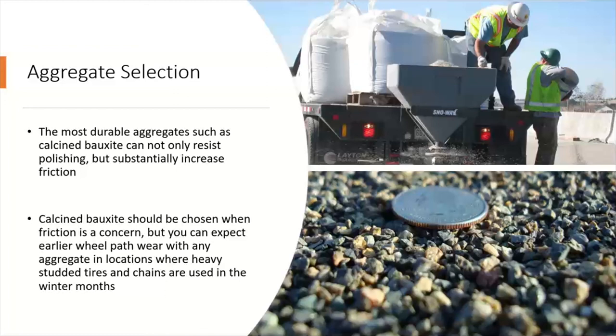It's calcinated and heated up to 1800 centigrade, and it's 87% aluminum oxide. So that's why it's really polish resistant. If you don't have a lot of traffic and you're more rural, you don't need calcined bauxite. It's very expensive. And even if you do use calcined bauxite, if you have heavy chains and studded tire traffic, it's not going to stop. The resin binder cannot hold up to studded tires forever. It just can't. The calcined bauxite might help for a period of time, but it's not going to solve all the problems.